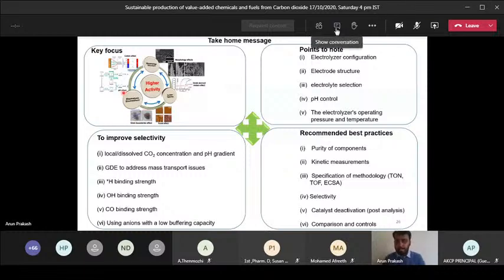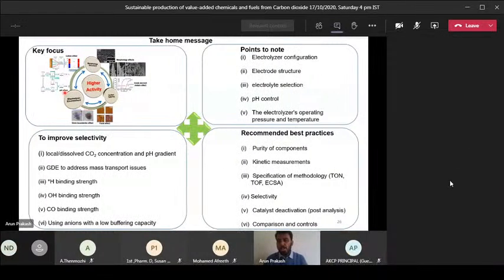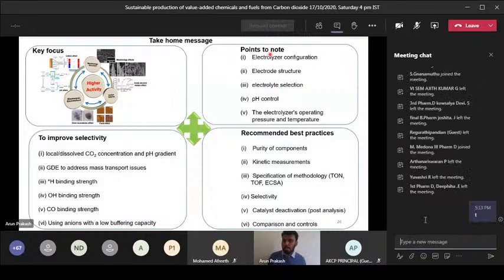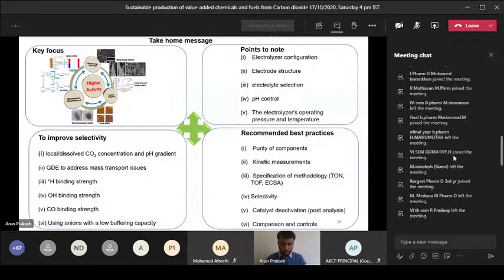And points to note, when you are dealing with a full cell like a CO2 electrolyzer instead of a half cell, you have to consider the electrolyzer configuration, cost, electrode structure, electrolyte selection, pH control or pH changes, and the electrolyzer's operating pressure and temperature. Because based on the pressure and temperature, your activity or your yield will change. So you have to focus on that. Also local dissolved CO2 concentration, pH gradient, and the GDE to address mass transport issues, and these binding energies.